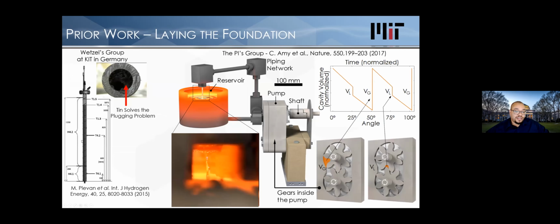What's shown on the left here, this is the group in Germany. They've made a reactor before. Their reactor was made out of stainless steel. Remember, we talked about making flowing liquid metal or putting liquid metal in contact with another solid metal as your containing material. Liquid metals love to corrode or dissolve other metals. And so their reactor had some issues because the tin started eating away at the steel. They couldn't go very hot. The hotter you go, the faster it happens.